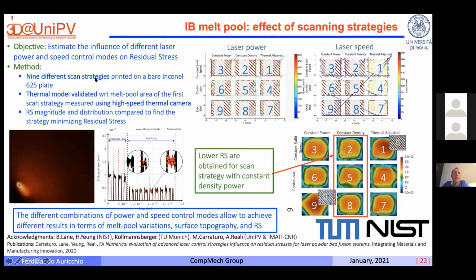So basically, once you have a numerical tool that's able to accurately predict what's happening in the material, you can start also to design, for example, your laser scan pattern in terms of power and speed, and try to optimize what's happening in the material. And again, you can see here some different numerical investigations, and we are trying to match with also experimental data, but the results seem to be very interesting and in the right direction.